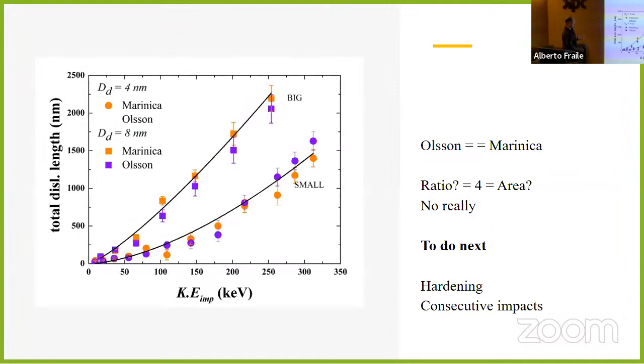That's why when we plot the results versus the kinetic energy, we have two sets of points. The results using the small projectile, the results using the big projectile, for example. And in this case, the results are not so potential dependent. You can see here both symbols are more or less on the same curve. Before it was potential dependent, but now it depends on the size. And now the ratio between these two is about 4. I thought it would be a matter of the size of the two impactors having this ratio, but it's not really 4. So this is being analyzed.